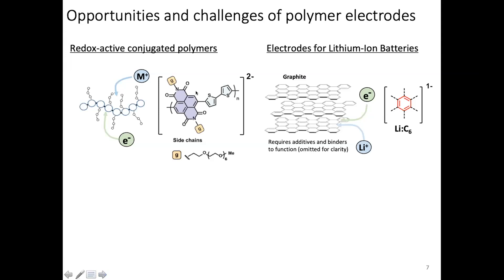Here is a typical material—an electron conductor. At a very simple level, you have to think of a molecule that will make electrons comfortable: things on the side that are electron withdrawing to decrease the energy level of electrons, so when you stuff an electron in, the material doesn't become unstable. This is a naphthalene diimide bithiophene molecule. What matters is that it can accept two electrons per monomer. The polar, glycolated side chains are sitting here. Compare this to graphite: you need a lot of this molecule to accommodate two electrons. In graphite, you only need six atoms to accommodate one electron.